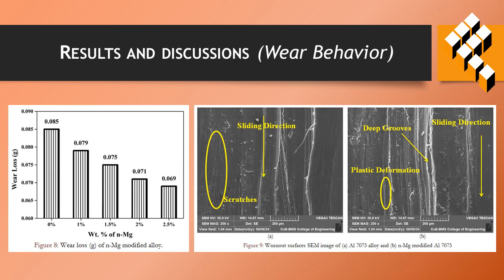Figure 8 shows the wear loss of the nanomagnesium modified alloy. Due to the high hardness, the material resisted wear and tear very well. So, by increasing the nanomagnesium particulates, the wear rate was reduced. Figure 9 shows the worn out surface of the base alloy and nanomagnesium modified alloy.